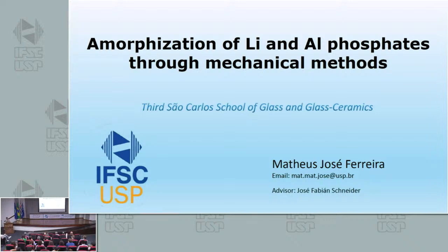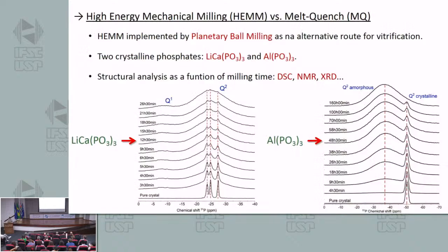My advisor is Professor José Schneider, and our work is about the amorphization of lithium and aluminum phosphates through mechanical methods. So in this work, we are using high-energy mechanical milling implemented by a planetary ball mill as an alternative route for vitrification, like usual melt-quench methods. In this work, we are currently studying the amorphization of two crystalline phosphates, lithium calcium and aluminum metaphosphates, and the